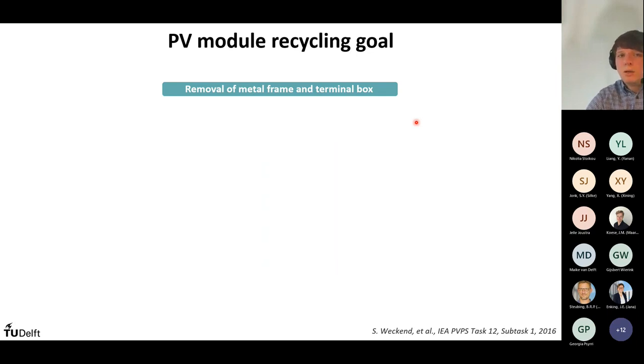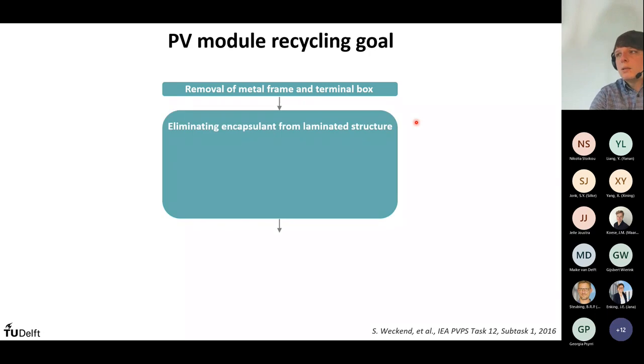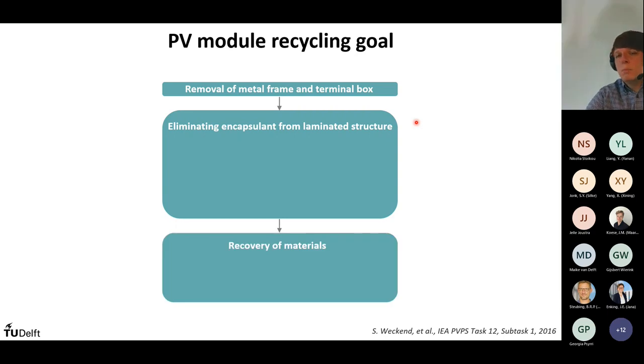So the first step is already happening today. We remove the external metal frame and the junction or terminal box, and then we get about 10% of the weight in external metal. Next, we crush the glass and we eliminate the encapsulation polymer, and this can be either burned away or removed by some chemical process, or it can be crushed and then separated. And then there should be a recovery of the silicon and the silver later on, which is the goal, which are the most valuable materials.